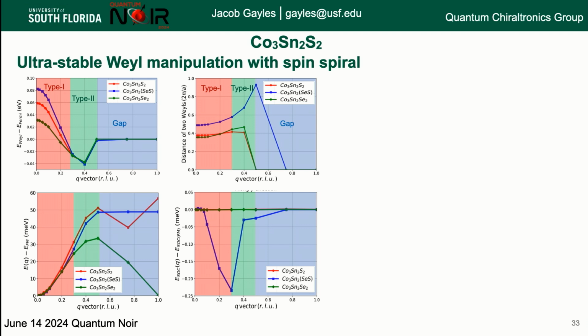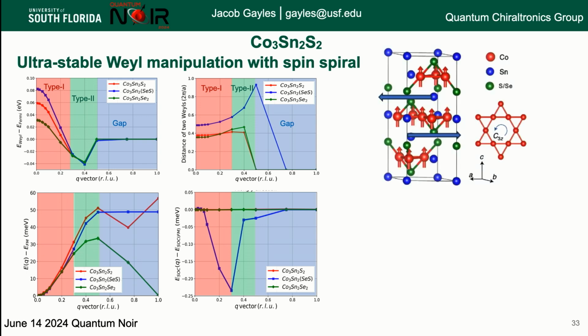And then here is the DMI, which is not a graph I would normally put, but it's actually not very large. It's not very interesting. It's not large enough to stabilize skyrmions. So then the next step was, okay, what's wrong there? And so we looked, which was my original prediction.